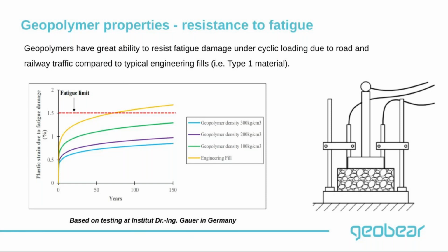Also, quite importantly, geopolymers have excellent properties to resist fatigue damage under cyclic loading. If you take a piece of geopolymer and cycle it for quite an extensive amount of traffic, you would end up with very little deformation in the long term. If you compare the fatigue performance of geopolymers with excellent engineering fills like type 1, for example, say you take the best type 1 you can find and apply loading cycles, it probably wouldn't last beyond 70 years in a typical railway environment. However, if you apply the same loading conditions on a geopolymer, it would last at least 120, 140 years easily with no problems.